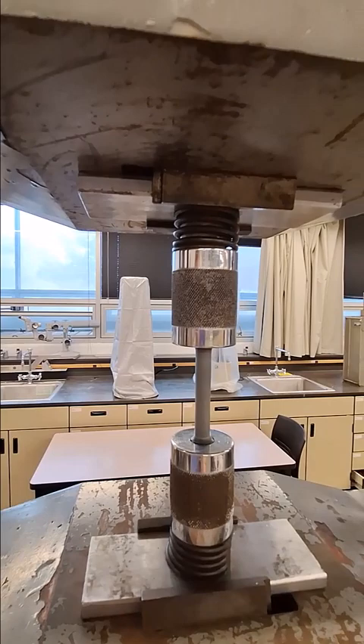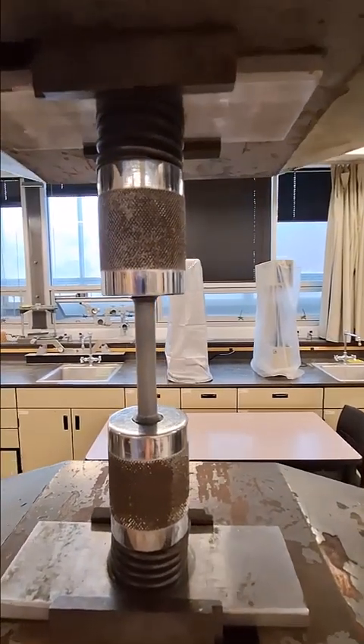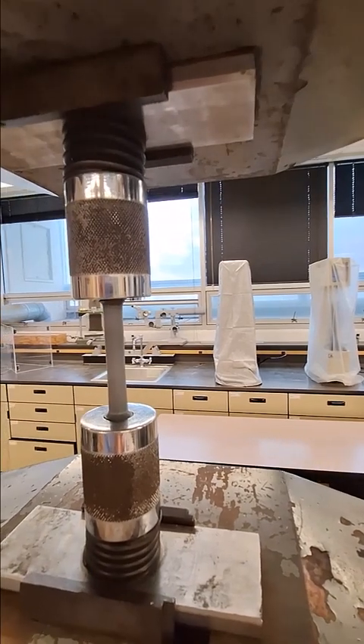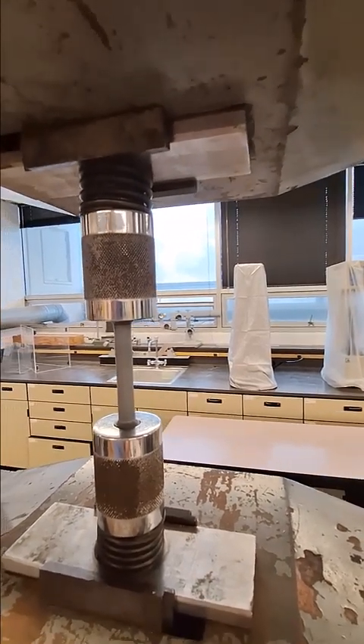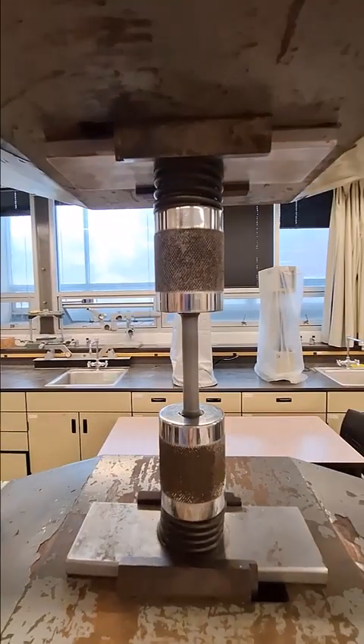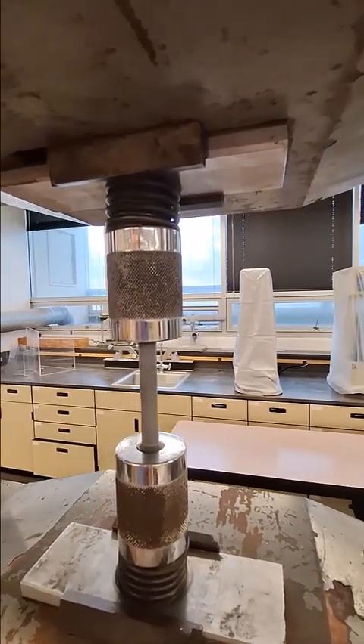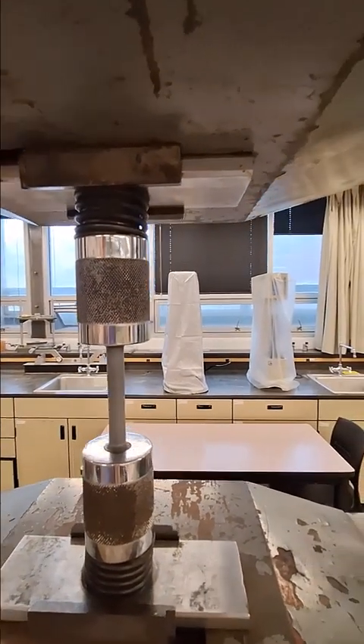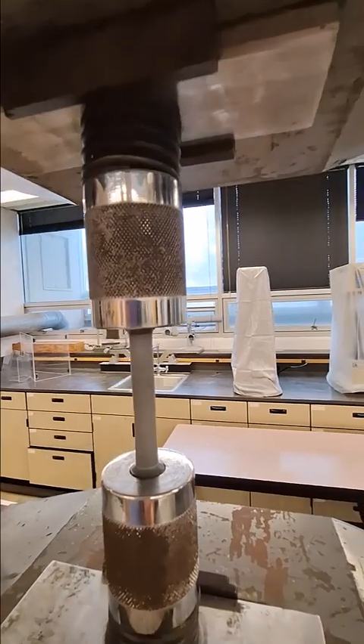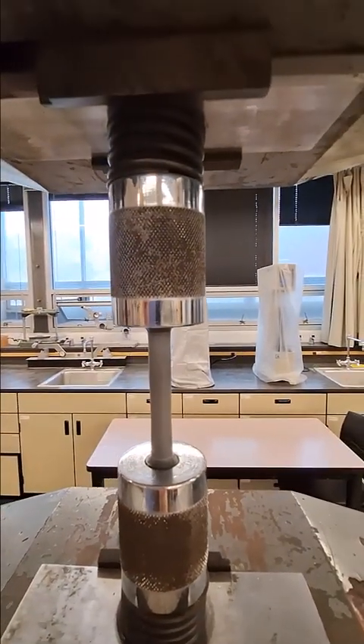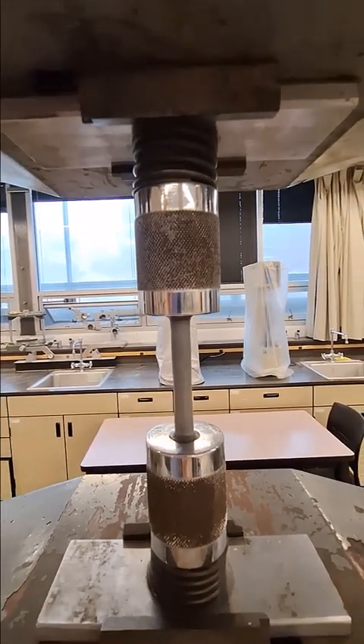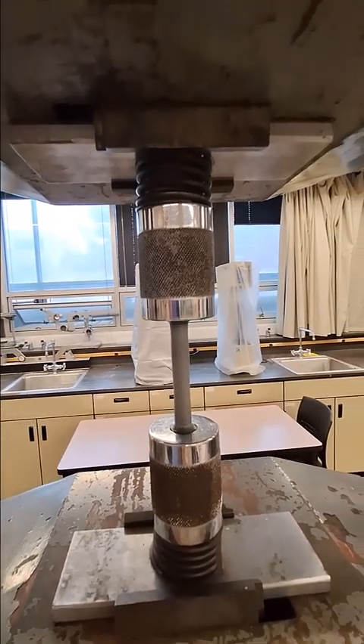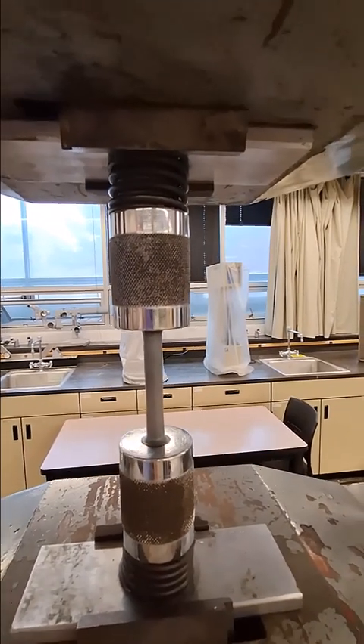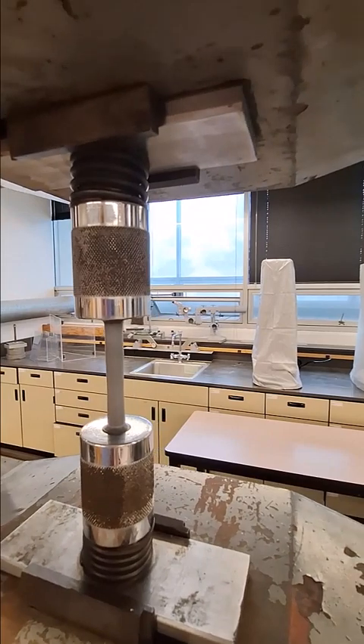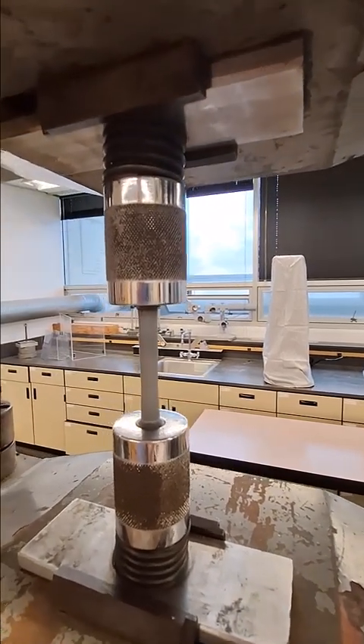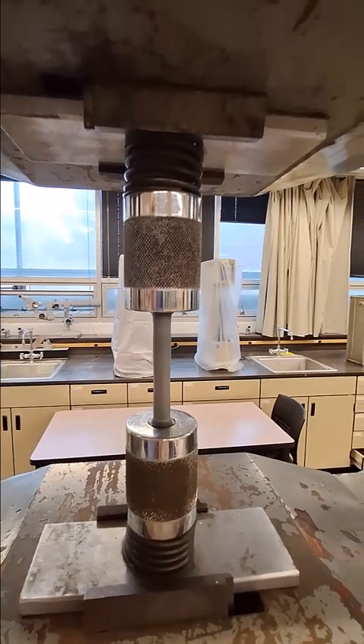Polystyrene is a fully amorphous material, meaning that the polymer chains are arranged in a spaghetti-like structure, completely random coil, whereas a semi-crystalline polymer like polyethylene, high-density polyethylene in particular, is going to have regions that are highly aligned, like lamella structures, which is like dried ramen. Now, when those chains are pulled apart, they are going to elongate, similar to how this polystyrene is, but because of those crystalline regions, they can actually start to recrystallize and stabilize the neck as it's pulled. Whereas with this material, you'll see once it starts to form the neck, failure is going to be coming soon after.